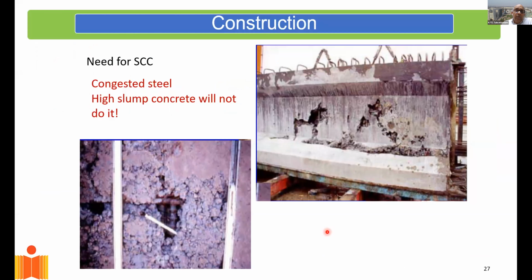Now, one step further. As we were going along, somewhere down the road, we realized that slump, as we looked at concrete, is not an adequate measure of flow behavior. Just to illustrate that, as we started building and using more and more steel to make longer span structures, the congestion in the steel started increasing. And what we understood about concrete at that time was slump. So at some point of time, it was realized that if I produce a high slump concrete, it still does not guarantee filling ability of the concrete. It just merely tells me that the concrete is slumping to a certain amount.